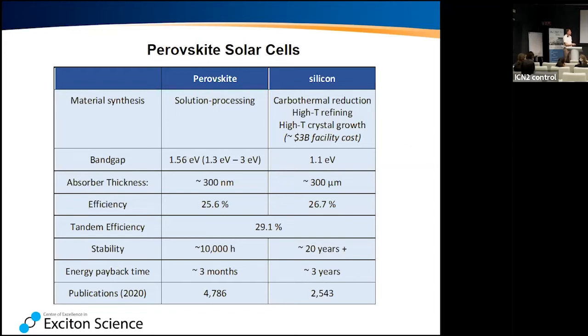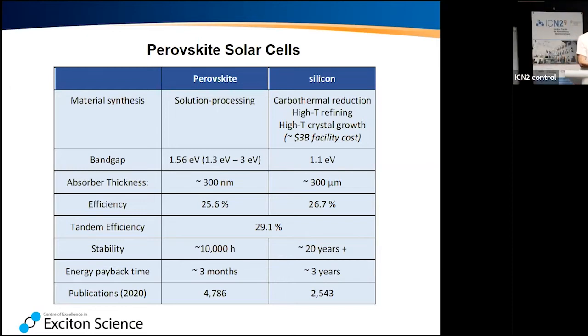The absorber thickness is typically about 1,000 times less than for silicon. Silicon is in the range of 300 micron, perovskite in the range of 300 nanometers. The efficiencies are very similar. Please don't beat me up if I have got those numbers slightly wrong, because they change every time. So we have efficiencies about 25.6 for the perovskite and just less than 1% more for the silicon. A nice thing is that you don't always have to think, are we better than silicon? You can combine perovskite with silicon. The last speaker we had comes from one of the world's best groups working on that combination of silicon and perovskite to make tandem solar cells. If you combine those two, you can get efficiencies up to 29%.